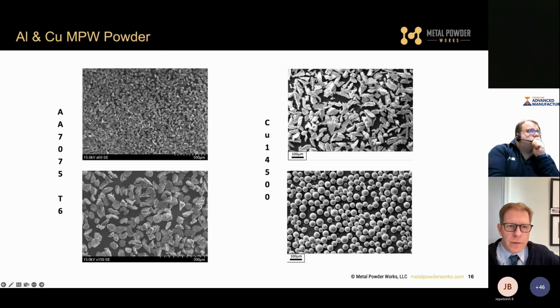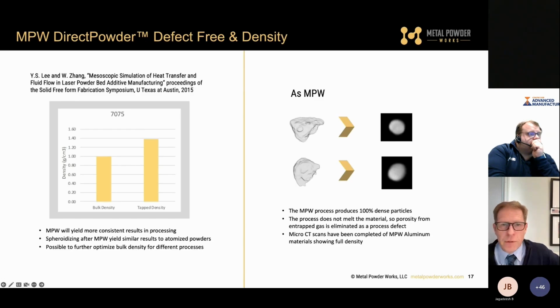Our aluminum and copper powder, here's what it looks like, is this prismoidal type shape. This can be further optimized. Here's another example where we took the copper material and ran it through a spheroidizer in concert with 6K, and get nice controllable spherical particles out of it. If you desire spherical particles, that's a possibility. We've certainly shown that it produces good prints in conventional processing through binder jetting and through powder bed fusion without it, but